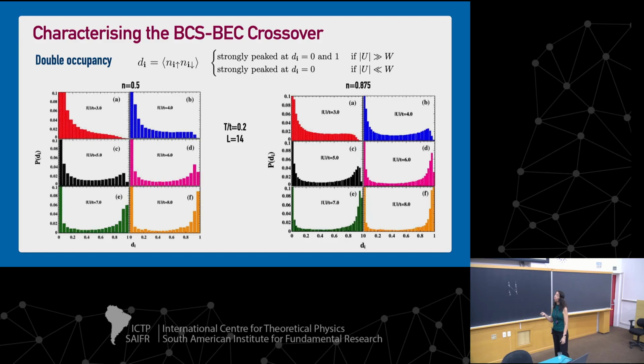So to characterize that, we are going to look at the double occupancy. What happens is, in one case, we have no pairs formed, we decrease the temperature, and the pairs form and get into the superfluid state at the same time. And in the other case, we had preformed pairs. So just analyzing the formation of pairs, we can see whether something is going on.